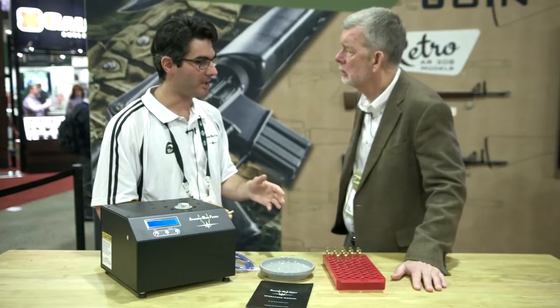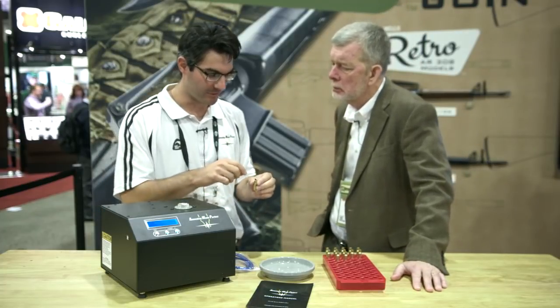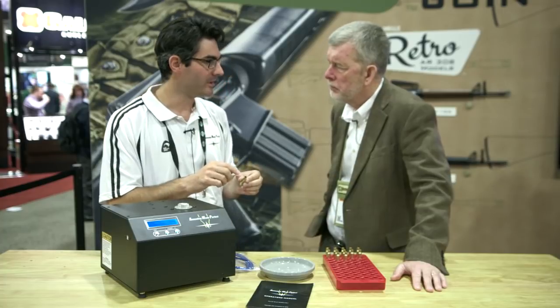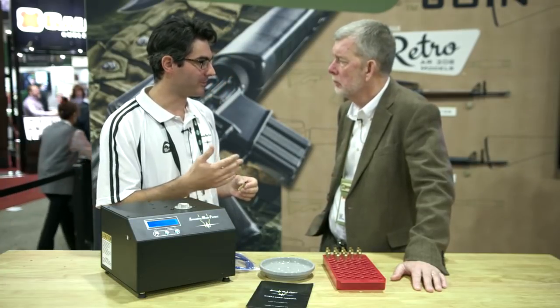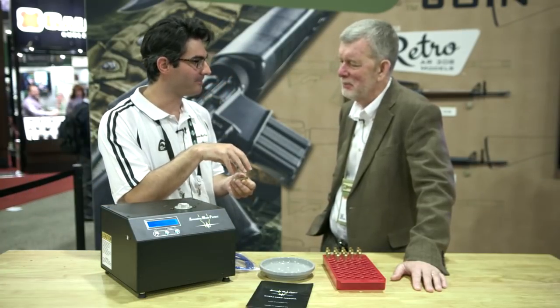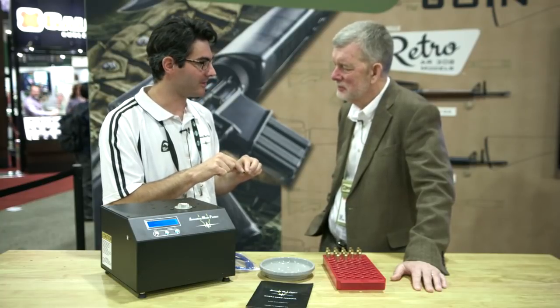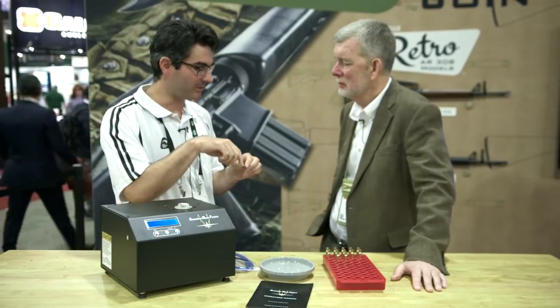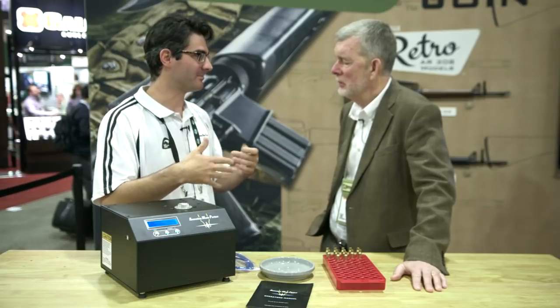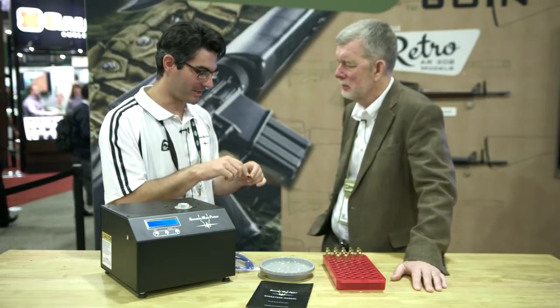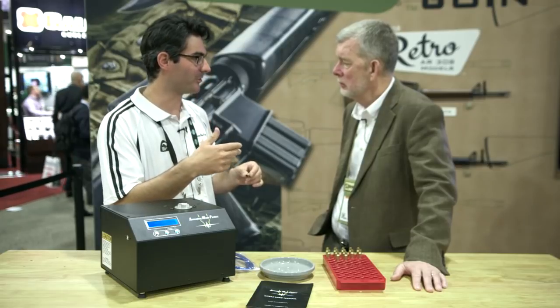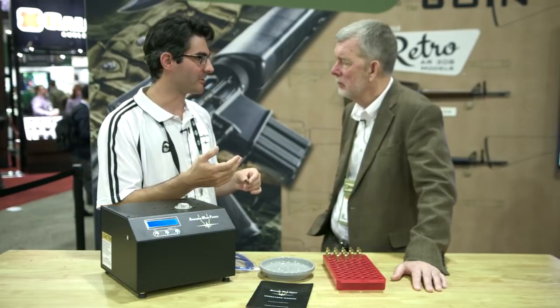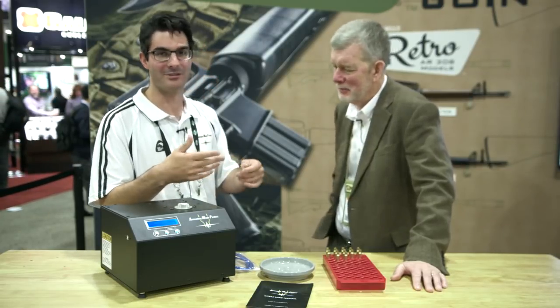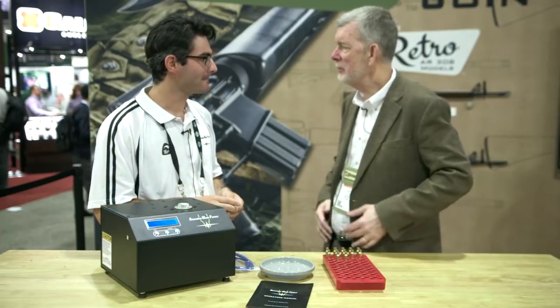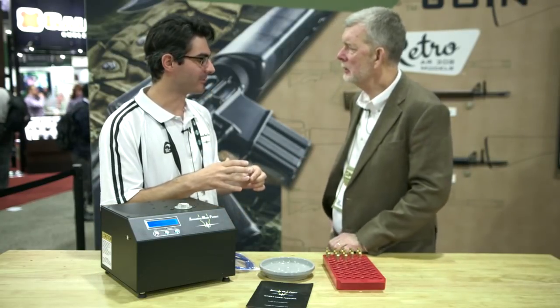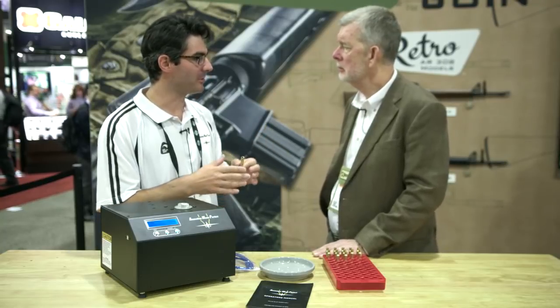It's important that it's micro Vickers, because what we've got here is a very thin wall, very thin neck wall. If you're trying to use Rockwell or something similar, the load is higher. And so what you end up doing is piercing the brass case here and going into your mandrel, and then you're actually artificially reading the mandrel and not the case. So you need a light load, which is why it's called micro Vickers. We're talking like grams instead of kgs or pounds, if you will. But tailor-made for this type of work, for very thin samples. So not normally cartridge cases, but anything that's thin.